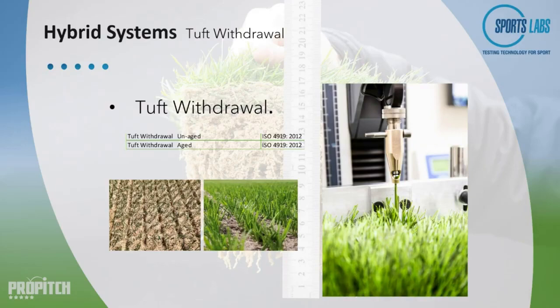The question is, would the EN minimum value of 30 newtons be more applicable for hybrid systems, given their construction? Or should we be looking at matching the FIFA and World Rugby requirements of 40 newtons? The tuft lock is crucial for hybrid systems, especially during routine pitch maintenance, any treatments of the surface that may be required or can influence the condition of the carpet, and of course during the renovation process. The renovation process could be quite aggressive for the yarns, and we're currently looking at replicating this renovation process in our laboratory on a full hybrid system to try and measure the effect on the yarns.